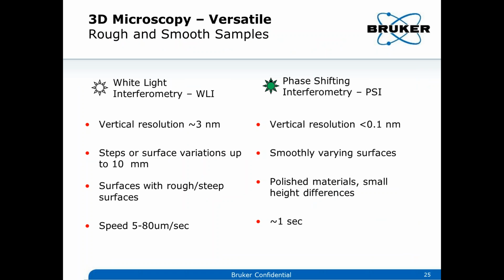So to summarize all the things that I mentioned: you have white light interferometry, or the VSI technique, vertical scanning interferometry, and then you have phase shifting interferometry, PSI. The vertical resolution of white light is 3 nanometers, and PSI is 0.1 nanometers, 1 angstrom. The roughness you can measure is up to 10 millimeters in a Bruker white light interferometry tool, from nanometer to 10 millimeter, so a big range. Whereas with the PSI technique, you're limited to lambda by 4, that's about 140 nanometer roughness. So if your Ra is below 140 nanometers, you can use the PSI technique.